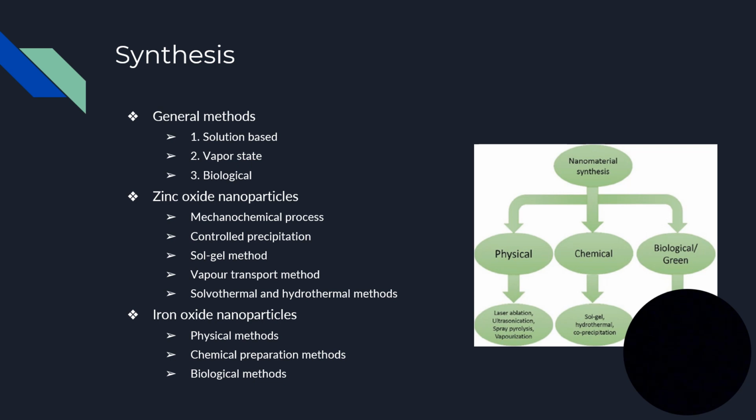These iron oxides can even be synthesized through co-precipitation of iron 2+ and iron 3+ by the addition of a base. All in all, the size, shape, and composition of iron nanoparticles synthesized through chemical methods depend on the type of salt used, the iron 2+ and iron 3+ ratio, pH, and ionic strength.